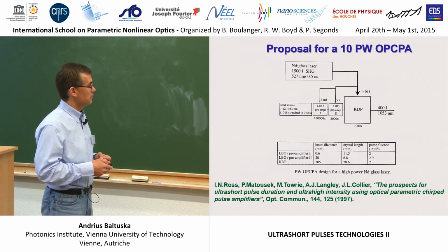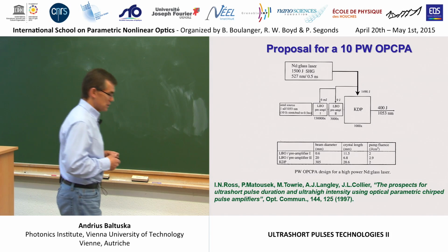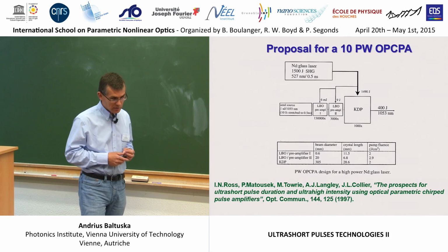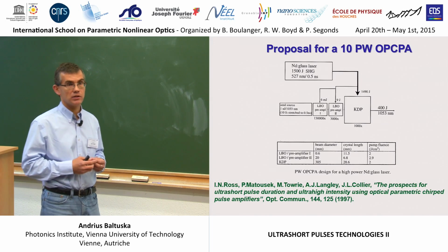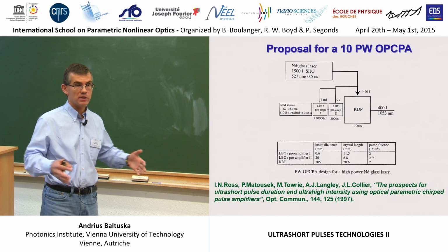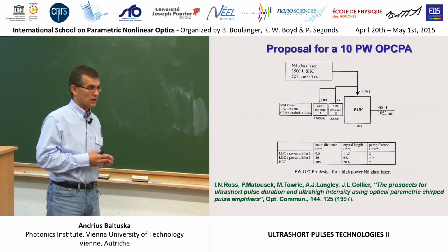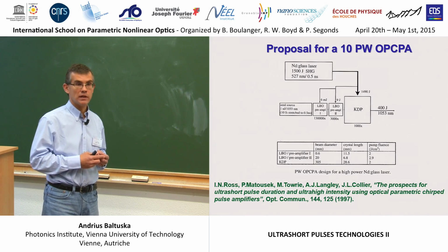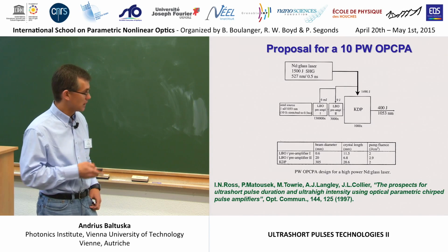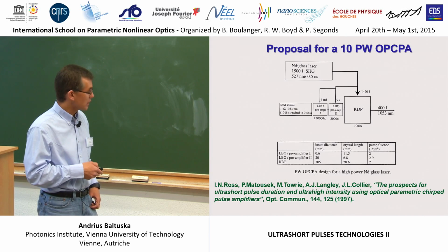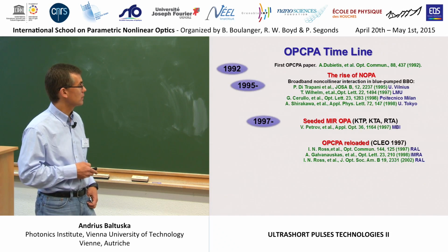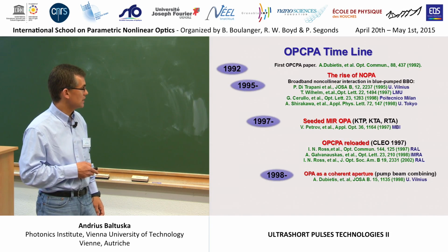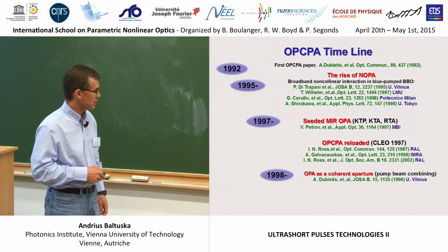And for this kind of ideas, still the best crystal is KDP or DKDP, and that's related to the size of the crystal that you can grow. For high energy applications, you would be frequently limited by the aperture of the crystal you can grow. For other nonlinear materials, as you have probably heard, it's kind of difficult to grow crystals in large sizes. So that was the trigger that created an avalanche, and the bandwagon started rolling of this OPCPA idea.